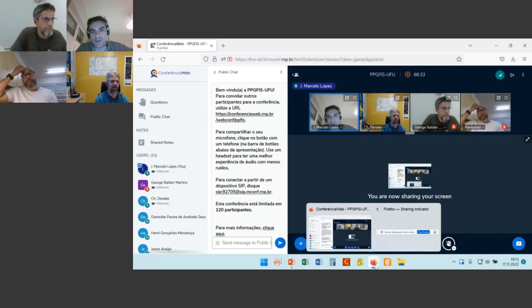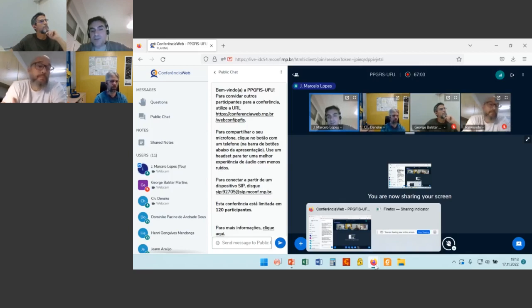And you've seen there, this van der Waals epitaxy is a wild horse thing. I guess what is well established nowadays is growth on metal surfaces. We worked also on that. I did not show it today, but growing hBN on a nickel surface, on a copper surface, or graphene on these surfaces, I would not say is easy, but it works quite nicely, right? And even MBE, I would say, is not the method of choice in that case. CVD is even better, but still it works quite nicely because you have a very strong atom diffusion at the surface and so on.